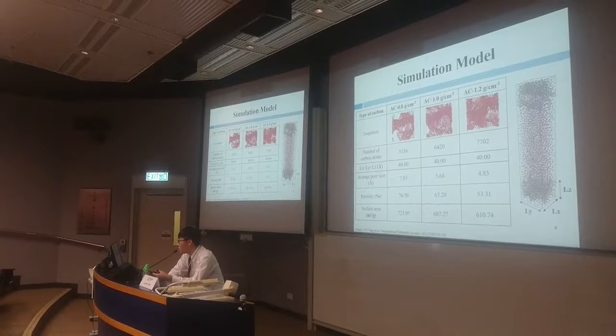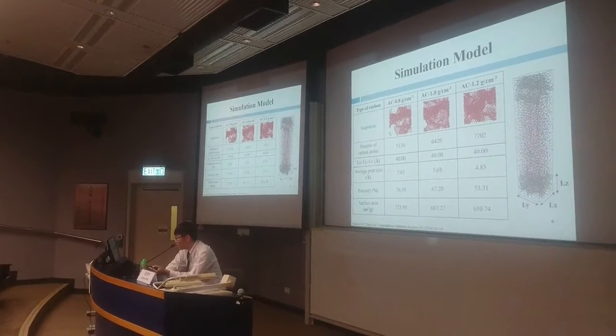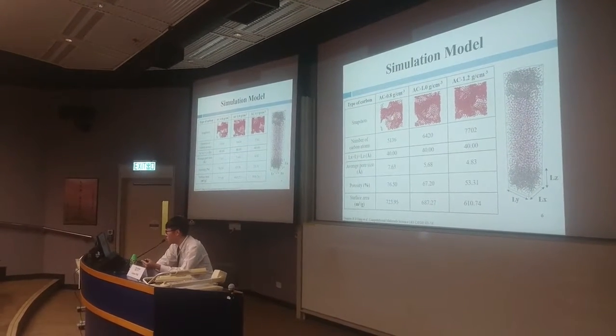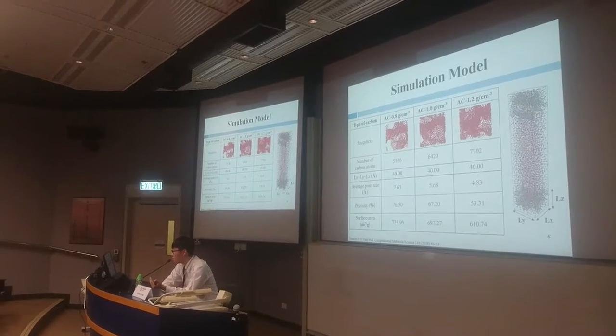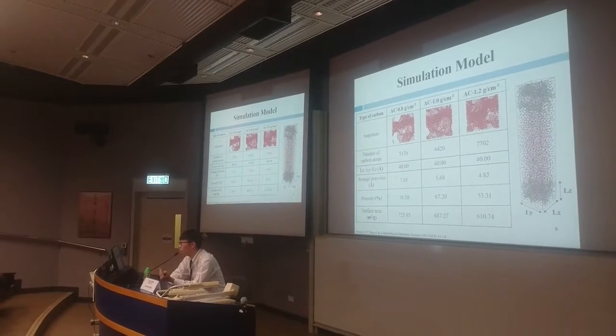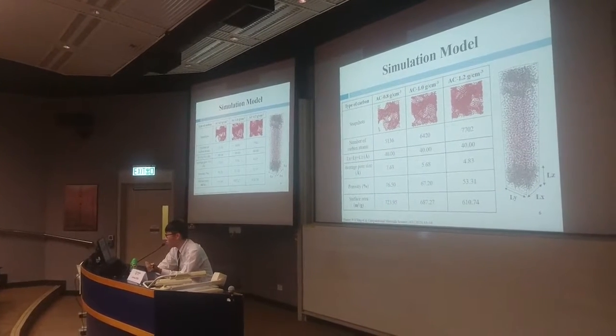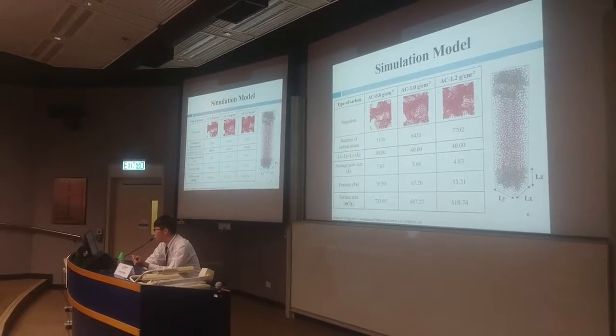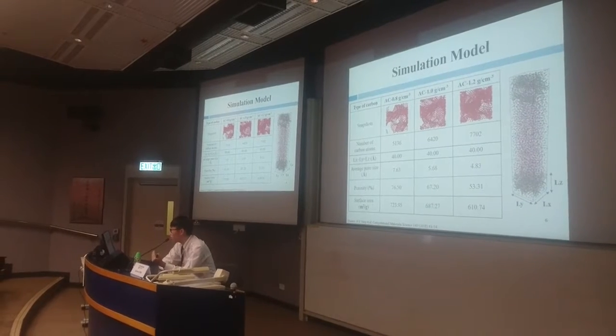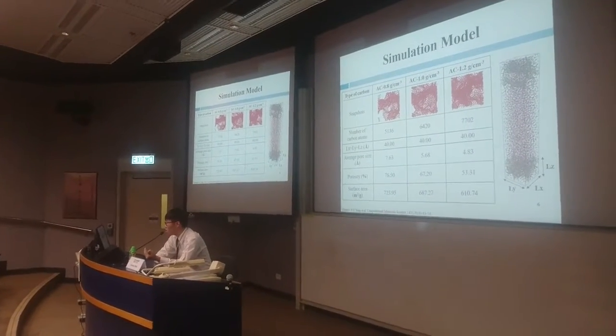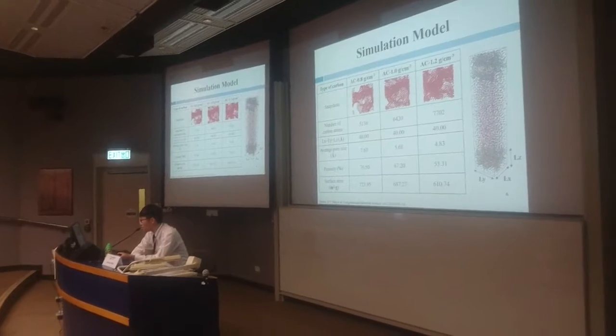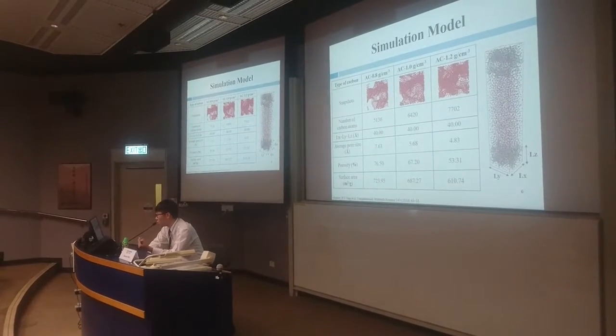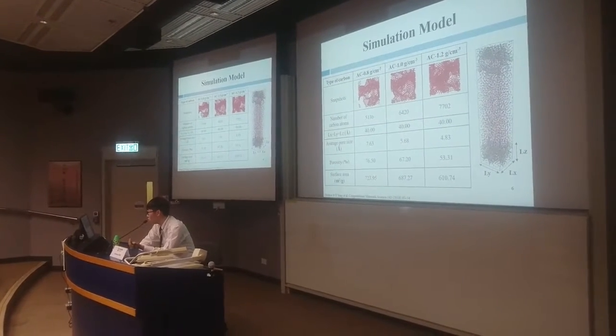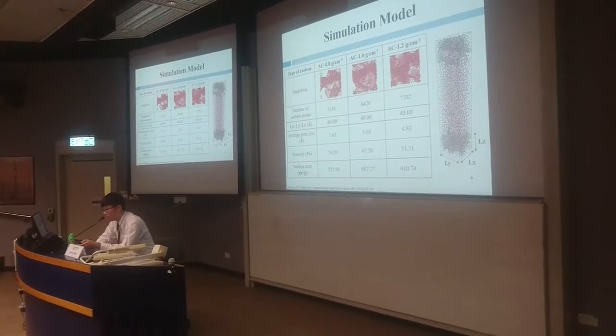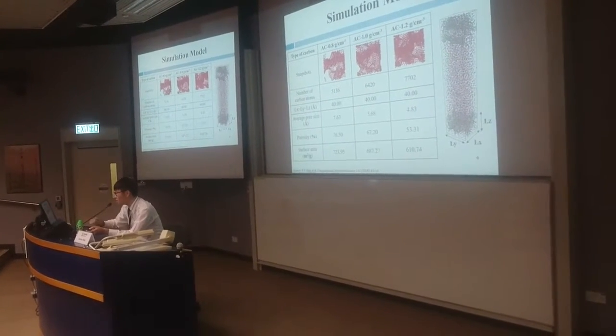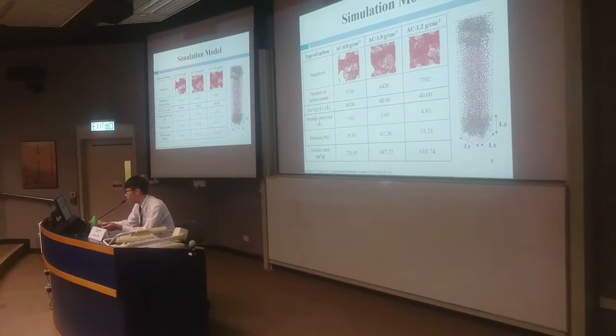In our previous work, we have successfully predicted the structure of AC by combining the Monte Carlo method and the simulated annealing method. So we use the same method to construct the EDLC model for this study. The structural properties of those models are shown in this table, including the average pore size, porosity, and the surface area.